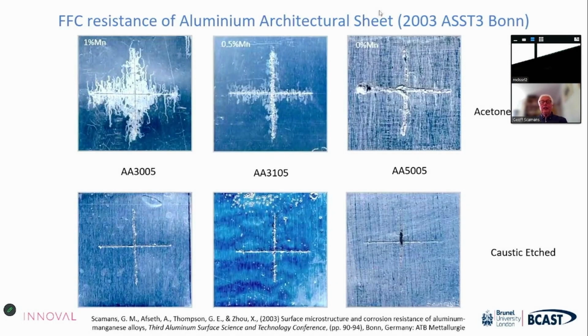And so it became very clear that if you wanted to control filiform corrosion in 3000 series aluminium products, one of the easiest things you could do is to drop the manganese content, or alternatively clean off the deformed surface layers. Both work really well. If you drop the manganese level from 1% to 0.5% of manganese, or even very low manganese in a 5000 series alloy, you can pretty well eliminate filiform corrosion.